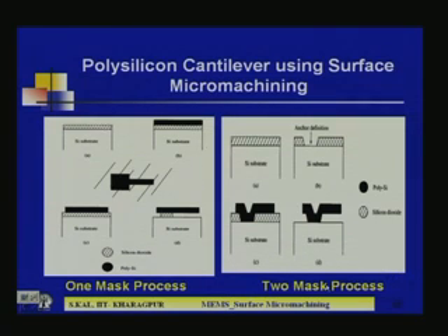Now, for the polysilicon cantilever using surface micromachining, there are two methods, one is known as the one mask process, the other as the two mask process. In some cases you need two masks, as I discussed in earlier view graphs. One mask patterns the sacrificial oxide, then another mask patterns the structural layer. That means the sacrificial layer patterning mask and the structural layer patterning mask; when you use both, it is known as the two mask process. On the other hand, you can go for only the one mask process also, but with some limitation. That difference is shown here.